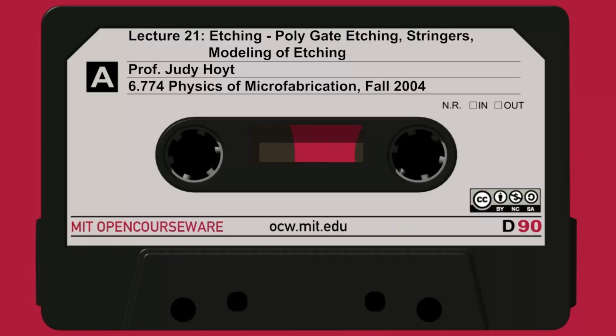What are some other materials? Those are the more common ones. Maybe a little less common, but things that you do have to etch often in plasmas are, for example, aluminum wiring or aluminum contacts. It's very common to use chlorinated species like chlorine or BCl3 or a mixture of chlorine and nitrogen. Chlorine itself can be somewhat isotropic, and some of these other gases are more anisotropic.